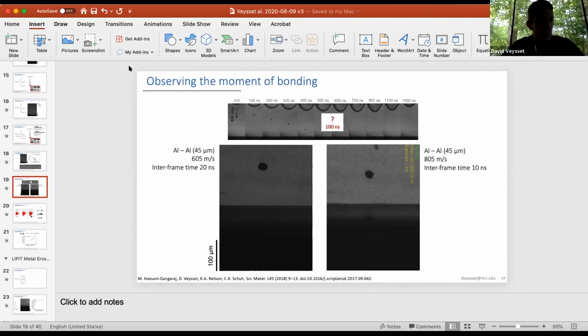That's the advantage, and that's what people doing cold spray actually use to promote their method, because under the right conditions, the bonding happens in the solid state. So you don't have any melt happening. This is why you can keep good mechanical properties without going through melting and what is associated with melting. Now in different work we've also shown that for some particle combinations and some velocities, as I showed for erosion, you can create a melt zone at the interface between the particle and the substrate.